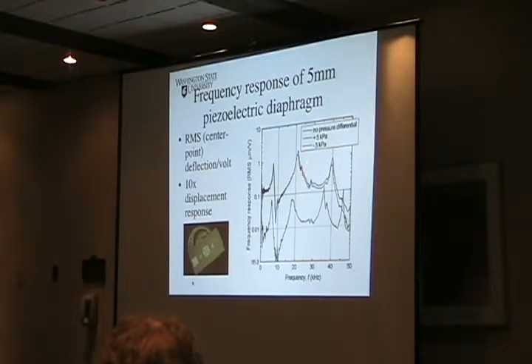And we find out that first off, as we pressurize the membrane, we can either push it outward or downward. So we can either pressurize back and forth. And when the membrane actually works for power generation, it oscillates somewhere around 0.